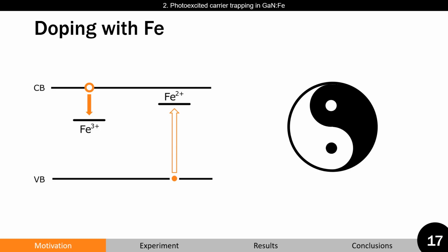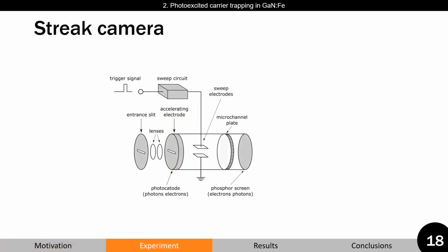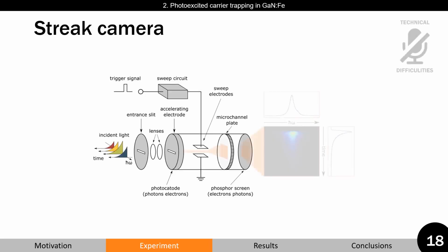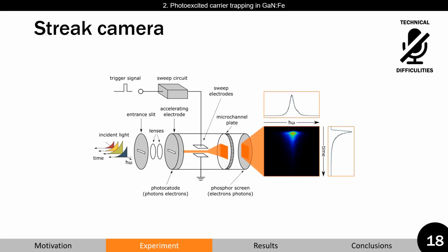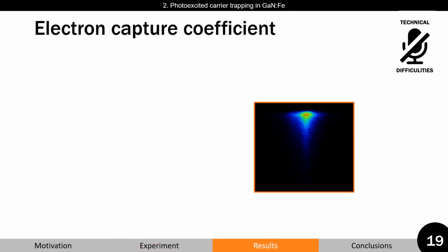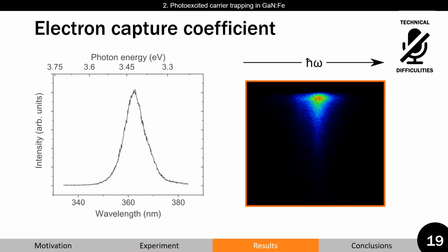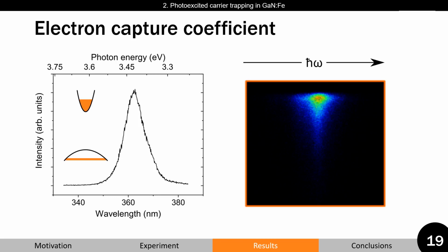dynamics should be understood. In this study, a streak camera was used, which allows resolving recombination in gallium nitride. One would expect that by doping with iron, deep states are introduced in the band gap, which should affect the recombination properties, photoluminescence transients.